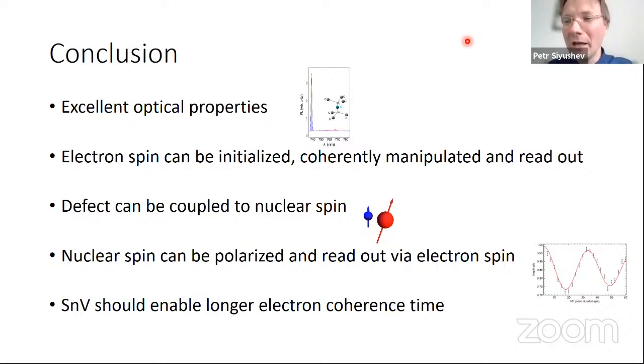And yeah, if you somehow can find out from which system it goes, either, for example, by frequency or mode or whatever, you won't create entanglement simply. That's the point. And I talk about good optical properties in the sense that the emission rate is very high. It's like for the silicon vacancy family of defects, and also that they are spectrally stable. They are predominantly associated with the zero phonon line, not with the phonon sideband, because the phonon sideband is associated only with incoherent photons. So that's what I'm talking about.